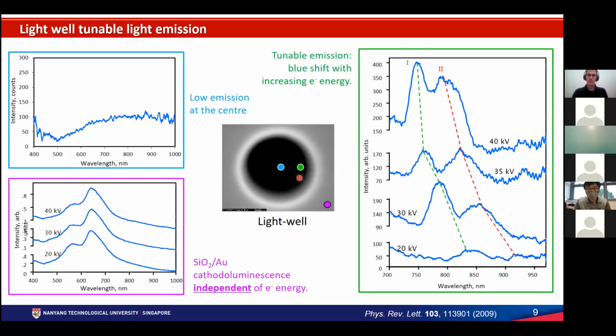Finally, when you approach the well, you observe clear peaks appear in emission, and they change spectral position when you modify the electron acceleration voltage. They blue shift when you increase it and red shift when you decrease it. This is all in line with the idea of the emission mechanism. Compared to a proper free electron laser, the emission mechanism we had in mind is called Smith-Purcell radiation, where a free electron travels on top of a grating, and the modulation of the dielectric environment felt by the electron beam allows the radiation to be emitted. And you have a proper correspondence between speed and wavelength of emission and angle of emission.